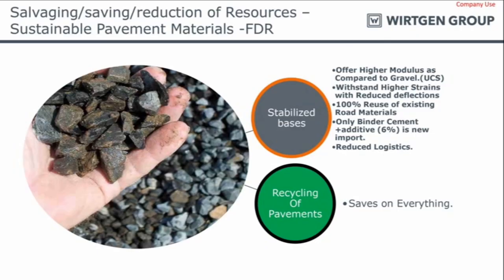As I said, we get a very high modulus while adopting this technology. The stabilized bases also offer a very high absorption of load transfer. Due to the reduced strains, your deflection on the upper part of the pavement is reduced. This gives you a longer service life of your pavement. With this technology, you are reusing 100% of your existing locally available materials, consisting of soil or aggregates. We require only 4 to 6% of additives. So we are cutting down on logistics, truck imports and carbon emissions. You're recycling everything. That's why it's called a green technology.